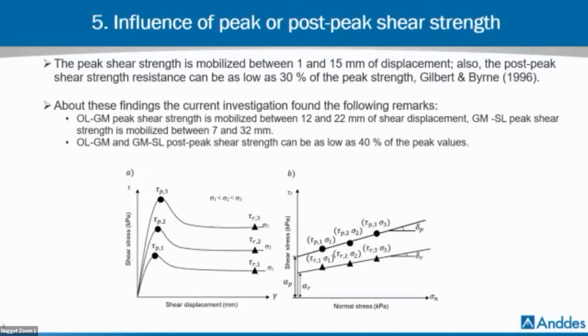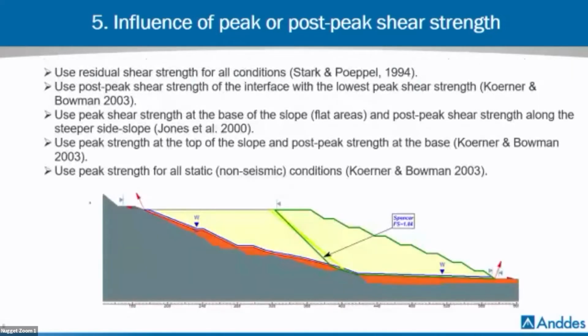So, what about the current investigation? We found that the overliner geomembrane interface peak shear strength is mobilized between 12 to 22 millimeters of shear displacement. And the geomembrane soil liner peak shear strength is mobilized between 7 to 32 millimeters. And the post-peak shear strength for both interfaces can be as low as 40% of the peak values. So, with this information it is logical to use the post-peak shear strength for the interface in the liner system design, due to the progressive failure across the liner, like the shear stress.